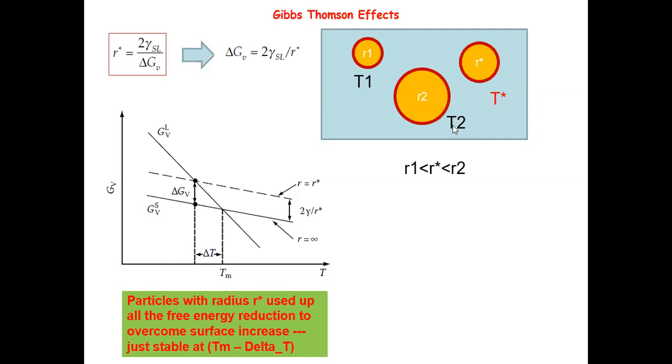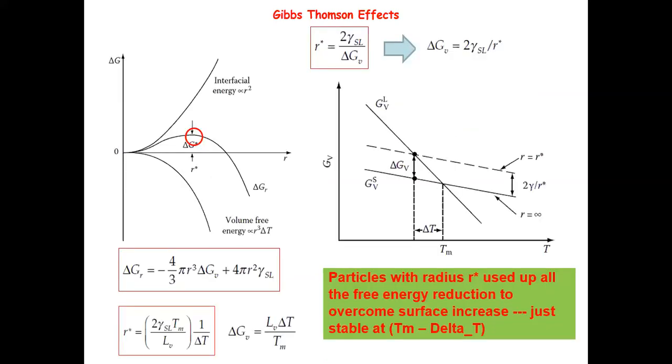Does that make sense? Yeah. So this means that in order for you to see the system start to nucleate, you can always have these smaller nuclei forming all the time, but they're not going to be helpful because they're going to melt back, wouldn't contribute to any subsequent phase transformation. So the minimum energy you need is going to be this guy.